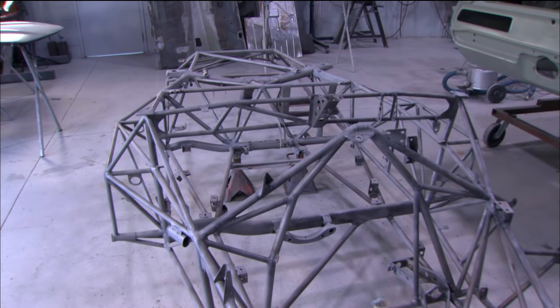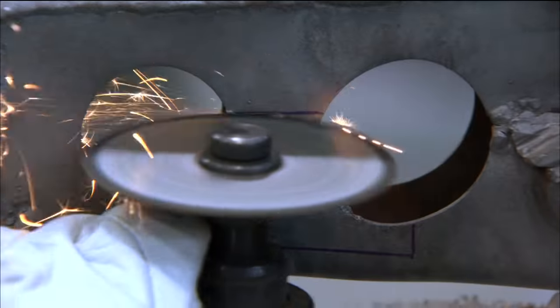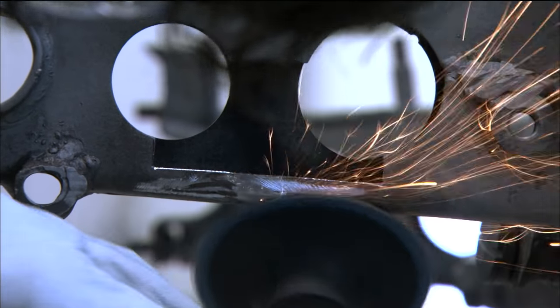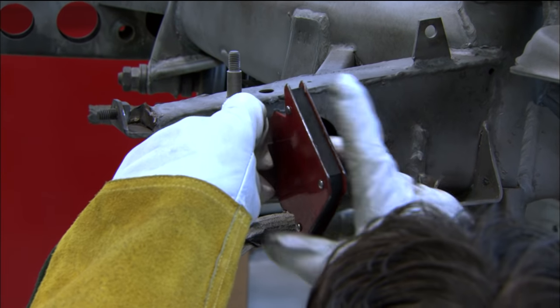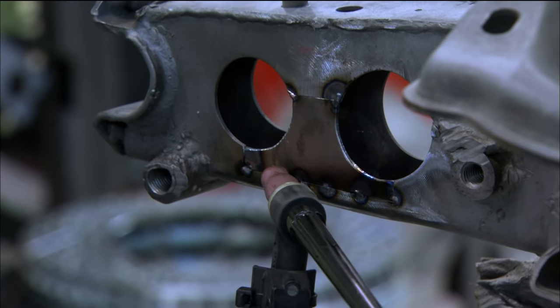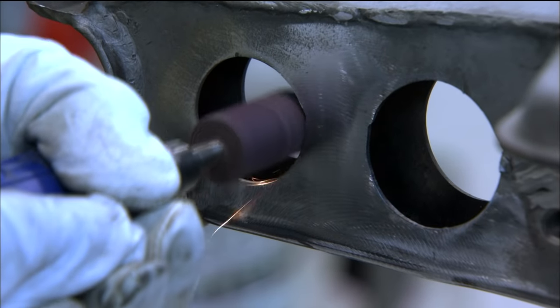After we got the frame back from the blasters, we found a couple of small items. The car had taken a light shot in the left front. Once we've got our piece roughly cut out to match the piece we're going to replace, we mark it, then use a cut-off wheel to precisely cut out the area. We're going to butt-weld this piece in, use a file to clean up the edges, and then a grinding disc to chamfer it. We use a magnet to hold it in place so it doesn't move as we tack it. The key to any thin-gauge sheet metal repair is to tack it first — don't solid-weld it anywhere. Distribute the heat. Because we're using a TIG machine, it's really not going to take much grinding to make the weld invisible. Once done, we clean up the edges with a Dremel tool so you're never going to cut yourself.